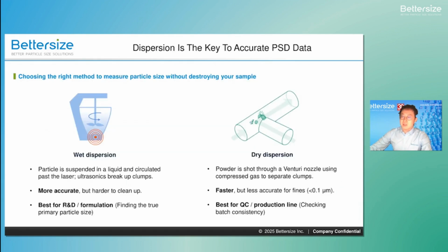Now we understand the theory. The practical challenge becomes dispersion - how to separate sticky particles to measure them individually. We have 2 main paths. Wet dispersion on the left uses solvents and ultrasound. It is the gold standard for R&D because it breaks up agglomerates for maximum accuracy. Dry dispersion on the right uses compressed gas. It offers the speed and repeatability needed for high volume quality control.